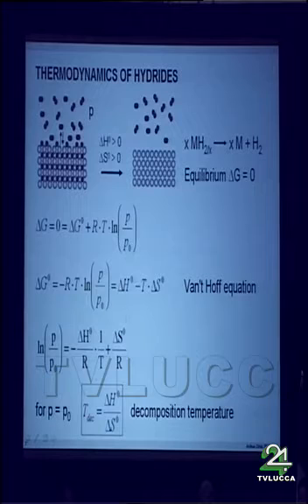So thermodynamically, I have shown before that due to this phase transition we see a plateau, and we can describe the formation, or here in this case the dissociation, the decomposition of a hydride, with the Gibbs free energy. And if we decompose the hydride, delta H is positive and delta S is positive. If we form the hydride, it's the other way around.